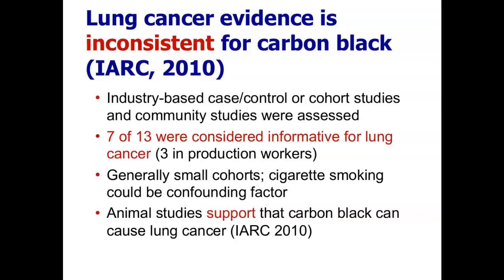However, the lung cancer evidence for carbon black is inconsistent. The worker that you just saw is from the 1940s in Texas. You might have noticed he was smoking a cigarette. The International Agency for Research on Cancer in 2010 indicated that after looking at all the industry-based case control studies, cohort studies, and community studies, there was some information. 7 of 13 were considered informative for lung cancer. And by the way, 3 of those were in production workers. But these were generally small cohorts, and cigarette smoking certainly could have been a confounding factor. It is important that animal studies do support that carbon black can cause some lung issues as well.